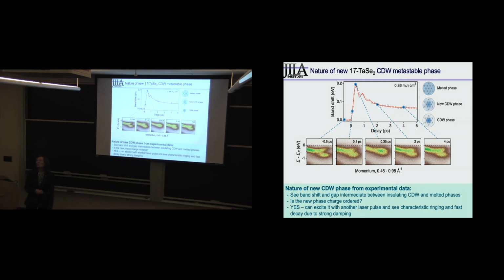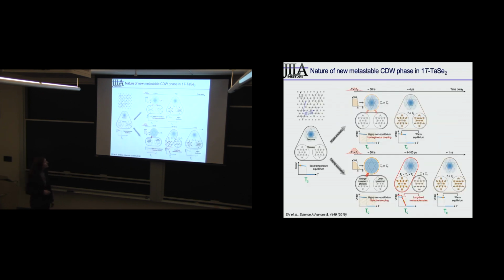We think it's a new charge density wave state because we can look at the band gap at each point, and sure enough, this band gap is sort of half this. This was one of our first experiments, and we've improved our energy resolution since. So what we think it is that we start in the charge density wave state, then very barely transiently melt, but this is a very distorted breathing mode because it's driven in quite an unusual way, and then it relaxes back to a new CDW phase that's very likely mediated by the fact that you've lost all the cross-plane phonons. So this is our cartoon for that.